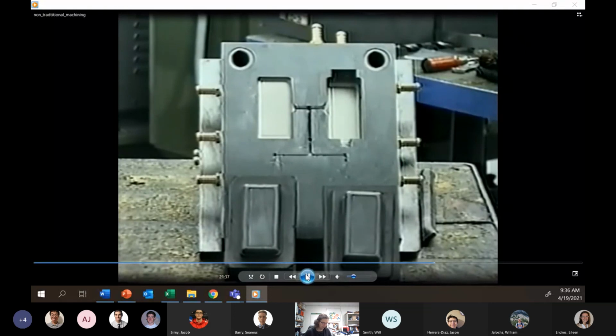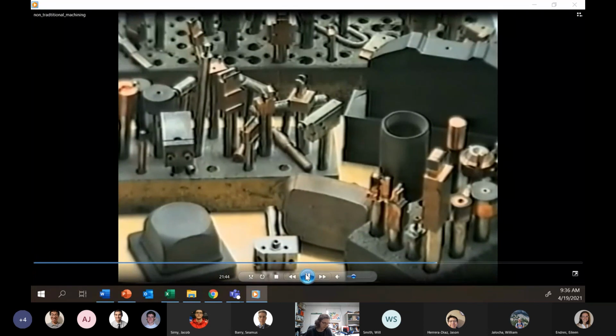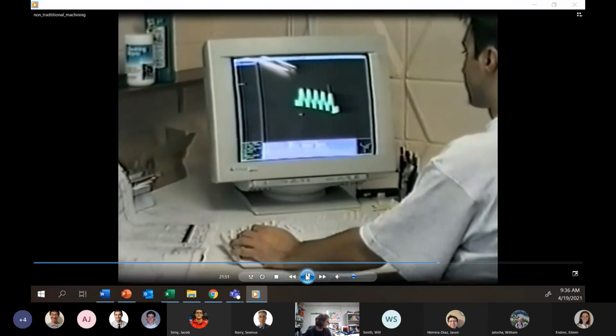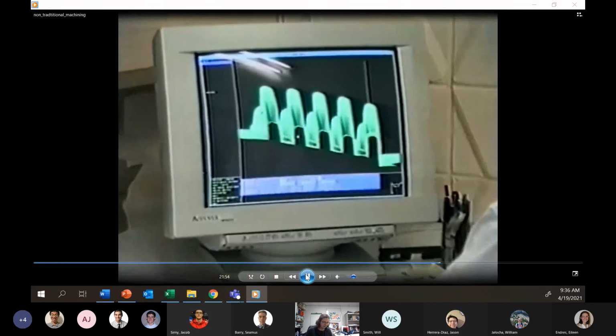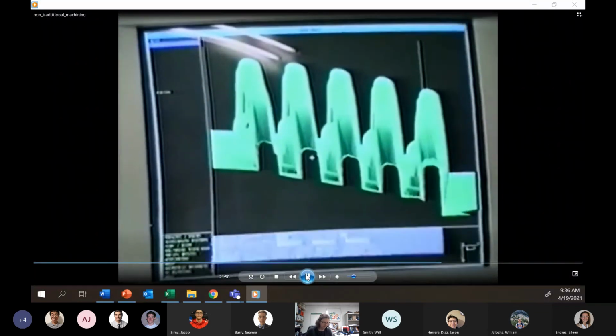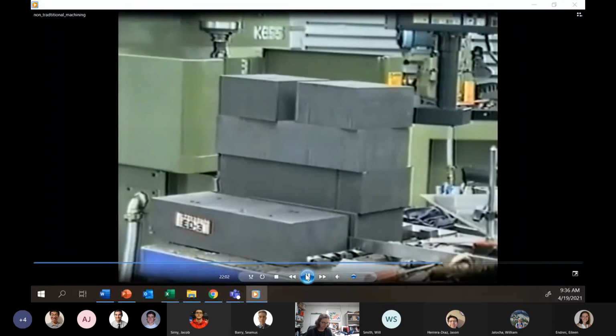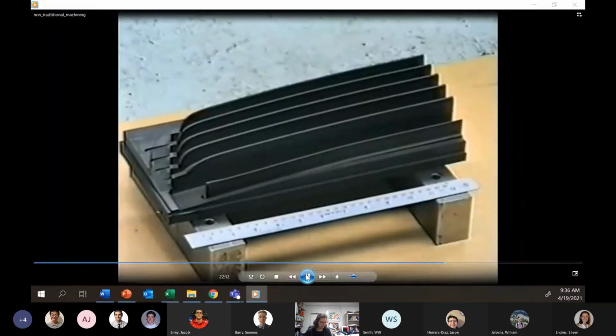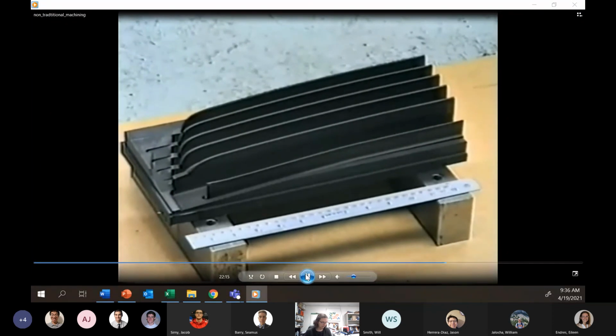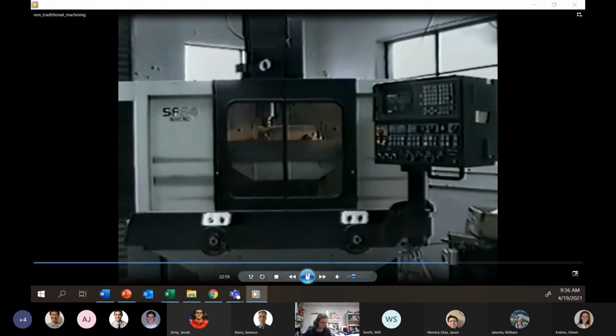The cavity in the die was cut using the graphite electrodes below. A new electrode is required for every new shape that is to be cut. With the advent of CAD workstations and CNC machining centres, very intricate and complex shapes can now be machined. The quality and cost of these graphite blocks varies greatly. The grade selected is dependent on whether a roughing cut or finishing cut is to be made and the rate of electrode loss that can be tolerated during the electro-machining process. The electrode shapes are produced using CNC machining centres having 3D capabilities.